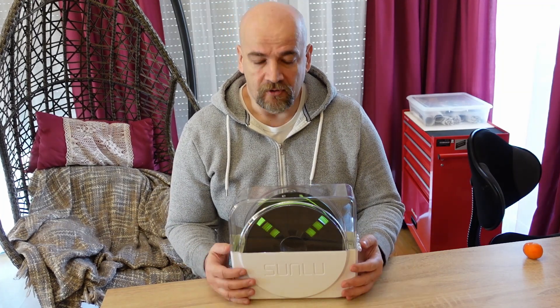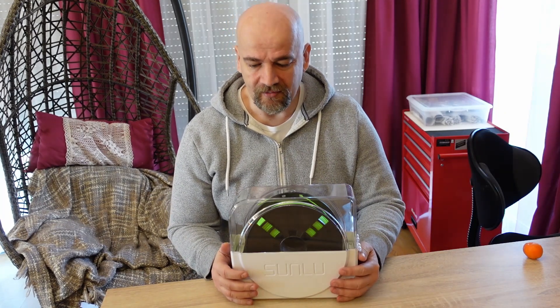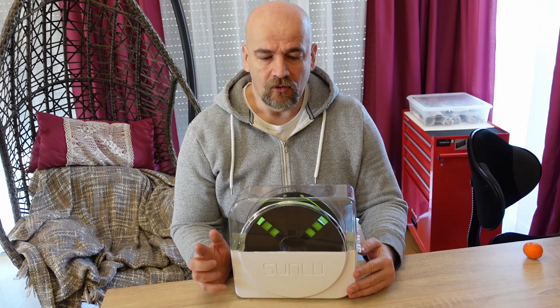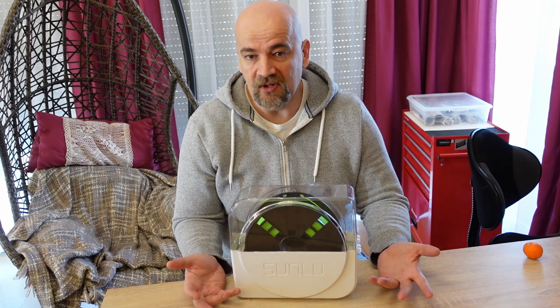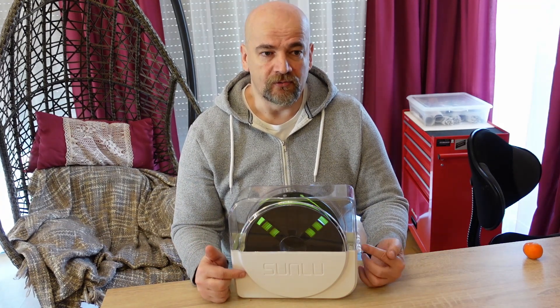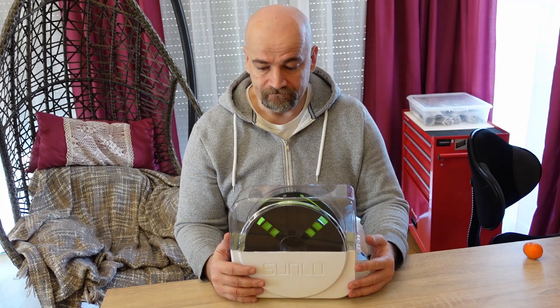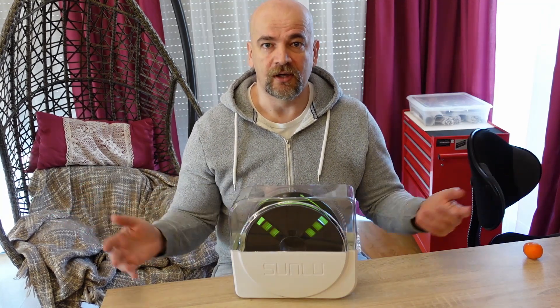The Sunlu filament dryer definitely works great with PETG. Of course those were really extreme test circumstances — it can even help with very old PLA that has stringing issues. Just pay attention to the recommended drying temperatures. Unfortunately with nylon, 12 hours at 55 degrees Celsius is not enough; maybe 24 hours would help. Let me know your experience with drying nylon in the comments. I'm curious to see how the E-Sun will perform with nylon drying, since its maximum temperature is 70 degrees Celsius. That will probably be my first video in 2021. Thank you for watching and happy printing!